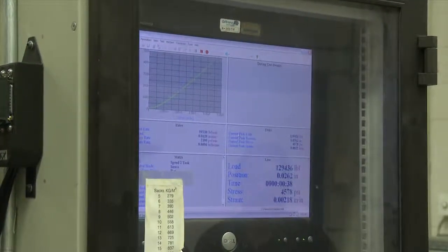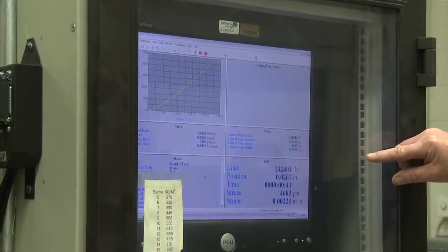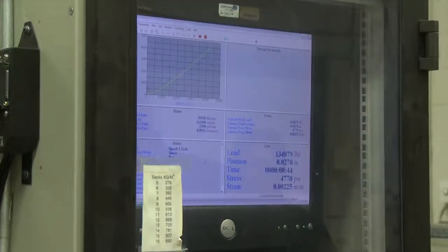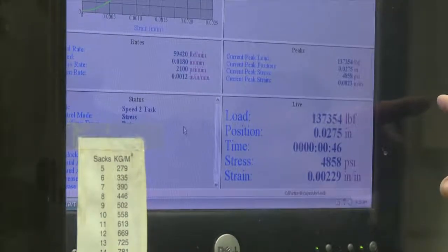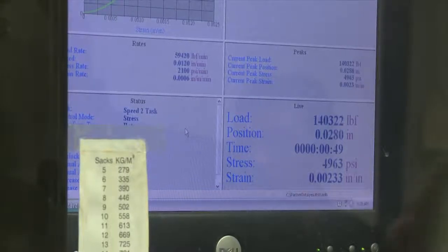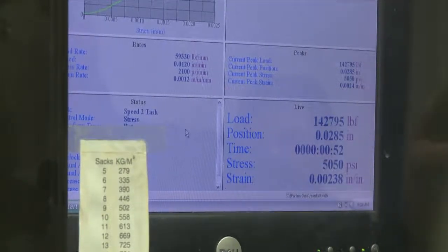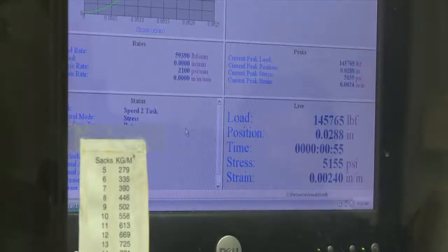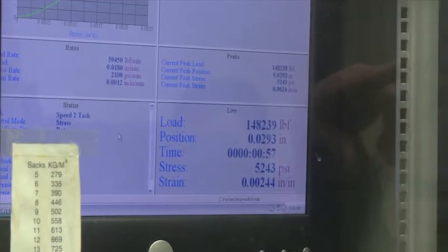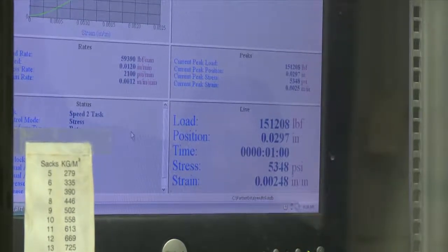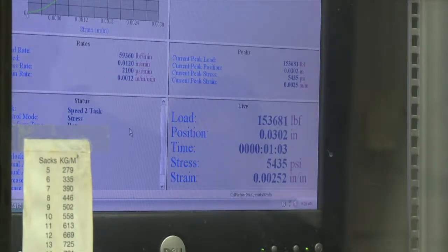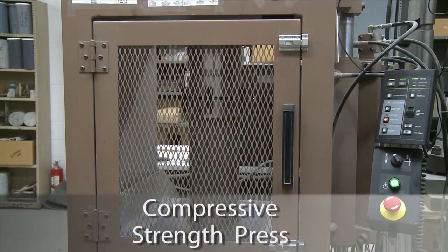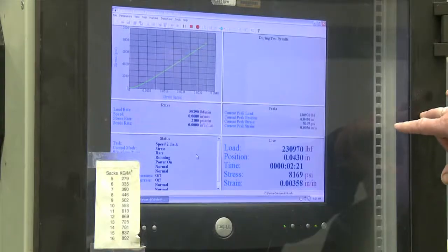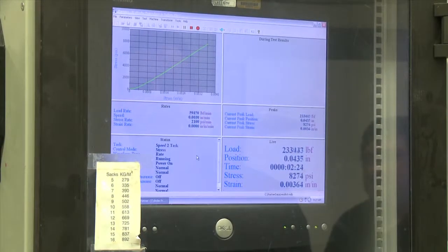We're already loaded at this. If you look here, this will give you the pound load that the cylinder is receiving. So we're up at 137,000 pounds. Using the cross-sectional area, you divide the total load by that, and it'll give you pounds per square inch, which we're already up to about 5,400 PSI. The load that's on that right now is 200,000 pounds and about 7,000 PSI. We're at 230,000 pound load and 8,200 PSI.